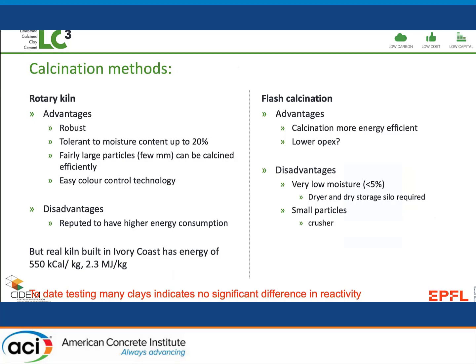Of course, the benefits of a rotary kiln, you can even use existing kilns. Recently, in a country I can't tell you, we actually shut down the clinker production, and within 4 hours, we were able to start calcining clay. So this just shows you with absolutely no adjustment, you can use the same equipment. Of course, if you want to make a production on a permanent basis, then it makes much more sense to get a separate calciner. And this can either be rotary kiln or flash calciner according to your preference.